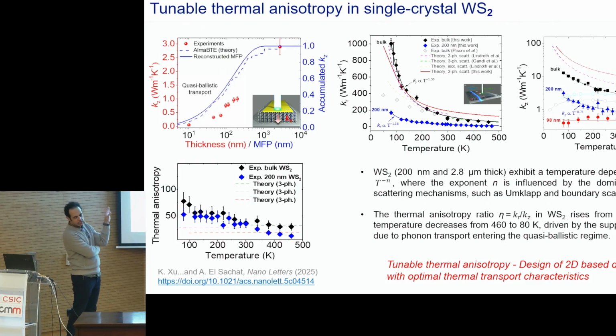So one big difference is that here it is exfoliated, single crystal. So we don't have any defects. Actually you see that the conductivity starts from 0.01, something very small, and goes until 1. So it's by a factor of 10 until 200 nanometers, which is something expected. This is what we found.